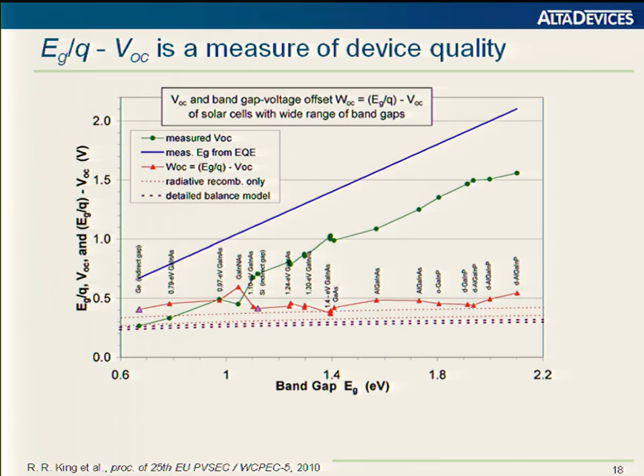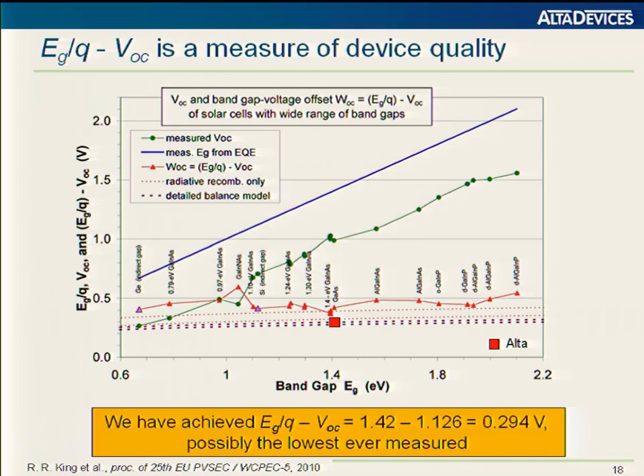The closer you can get the VOC to be equal to the band gap, the better the performance of the device, obviously. And a rule of thumb in this field is typically that if you're around 0.4, you're in pretty good shape as far as this quantity W. With this cell, actually the 1.126 VOC cell, achieved W values that are below 0.3 volts, which I believe are the lowest that have been demonstrated, and right near the theoretical limits, according to Richard King's graph.